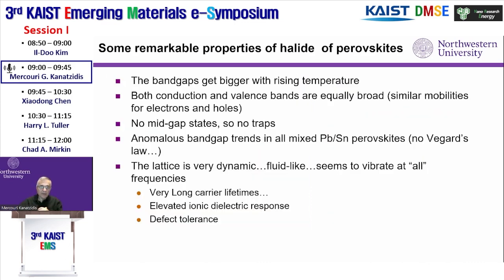So what are some of the remarkable properties of the halide perovskites? One is the band gaps. They're direct, and they get bigger with rising temperature. Normally, the band gap of a semiconductor gets smaller with rising temperature because of thermal band broadening. These band gaps are opposite to what we know; they get bigger. I will explain why later. That makes them stable at high temperature. Both the conduction band and valence band are equally broad, which I already talked about, with similar hole and electron masses. There are no mid-gap states and very few traps that will trap the carriers. Very important: when you mix lead and tin, there's an anomalous band gap trend that is very useful to the device community. I will talk about that too.